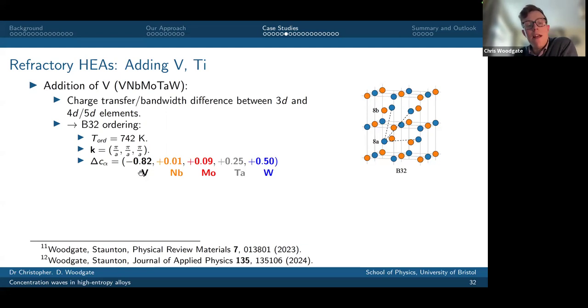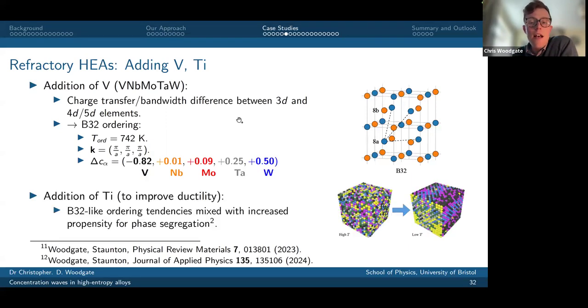And you find that this is dominated by vanadium moving to one sublattice. And essentially, niobium and molybdenum are relatively unaffected by the concentration wave, actually, but it's tantalum and tungsten moving to the other sublattice. Okay, and that's nicely in agreement with the sort of results people have found using other modeling approaches, so things like cluster expansion. So we were very happy with this.